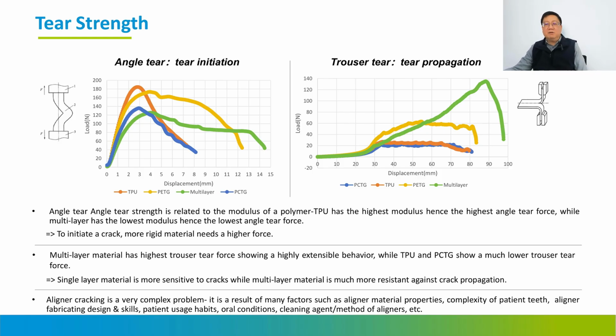So I will give you some examples about the crack resistance. According to our customers' statistics, about 1 or 2 cases per 10,000 cases have this kind of crack issue. But if you go for copolyester, then normally it is about 2 to 3% crack issue. For this reason, multi-layer is becoming more and more popular.